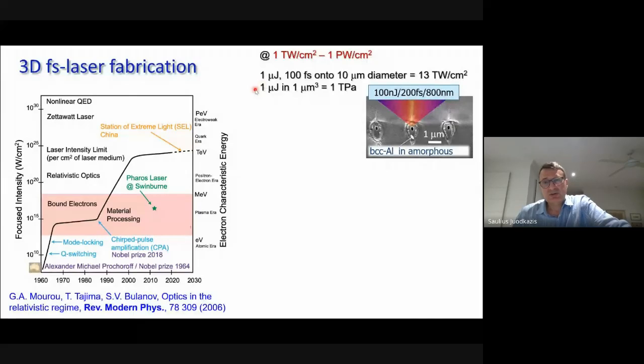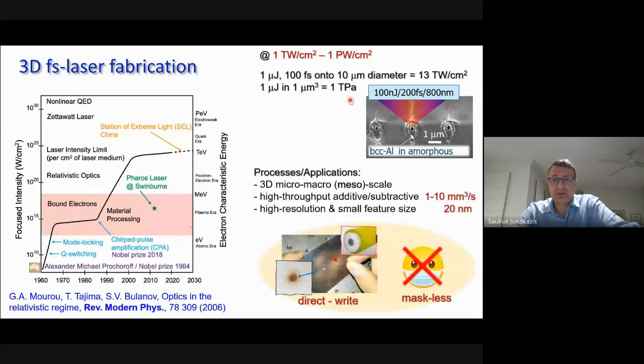And if you look at the conditions, what is happening if we take this 1 microjoule and deposit it into 1 cubic micron, which is a small volume comparable with the wavelength. So we reach the intensity, the energy in volume. This is force per square area, so it is actually pressure. So we have pressures which exceed pressures in the center of our planet, but these are certainly dynamic pressures which we can apply. Again, this is the tool which we can apply precisely, and we can modify material.